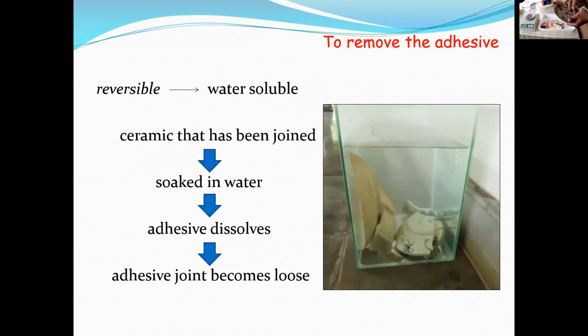Ceramic artifact repaired with animal-based protein adhesive must be stored indoor. It must be kept away from direct water contact, such as rainwater. So the weakness of the artifact being repaired using this natural adhesive is that it cannot be in contact with any type of water. But this is also its most advantage point, because if you make mistake in joining them during repair, you can easily fix them. If we try to dissolve the glue, it is better to use hot water because it will dissolve the adhesive faster.